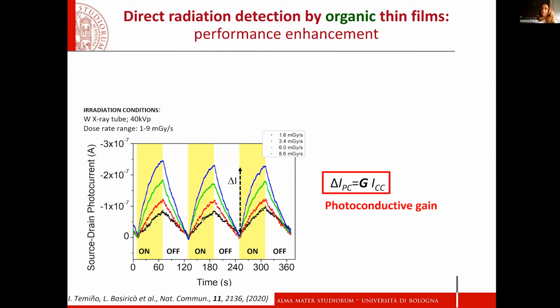the exposure to X-rays. So you see here reported an on-off response of the material, the device I was showing you before, to a 40 kilovolt X-ray beam. You clearly see that the material provides a strong delta I, reproducible, and the different curves refer to different dose rates, so to different fluxes.